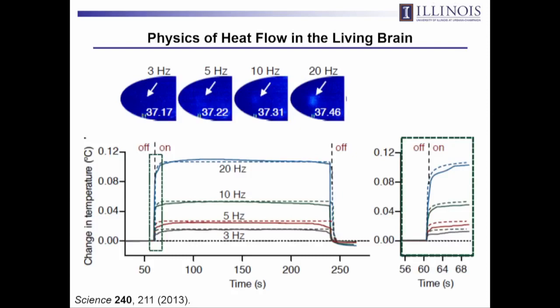I mean, you think about an LED flashlight or a headlight, you've got massive metal heat sinks trying to manage thermal flow, and the brain is tough because it starts to degrade permanently for increases of temperature more than about 1 to 2 degrees Celsius, that's it. So the thermal budget is very, very challenging, but it turns out that this works, and we did a lot of studies on the thermal physics before getting these things into animals to make sure that this was going to be feasible. And it works for 3 reasons. One is the LEDs are super small, so the surface area to volume ratios are very high, so the passive rate of thermal diffusion is very high, so that's good.